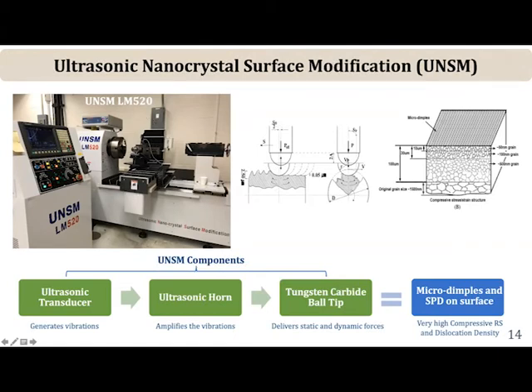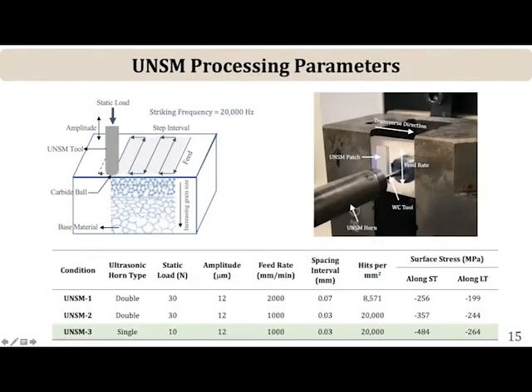You can even do cylindrical parts, and you place your sample or your coupons out here, and essentially what you do is you hit the surface and you create a patch, and you can vary the speed at which you move the tool, and you can vary the amplitude, as well as the pitch or the distance between the hits. So you can see that he chose three different conditions here for looking at the effect of UNSM.